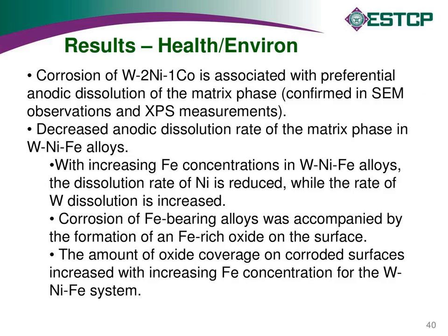And so I think the main thing to take away from this is, in any case, the corrosion of the tungsten nickel cobalt alloys is associated with preferential anodic dissolution of the matrix phase, confirmed in a number of different cases. And you have a decreased dissolution rate in any of the tungsten nickel iron alloys. And there's some evidence that as you increase the iron concentrations, you decrease the dissolution of nickel. And in some cases, though this is a little bit counterintuitive, you can increase the rate that the tungsten is dissolved. Although in this case, that may not be all that bad.